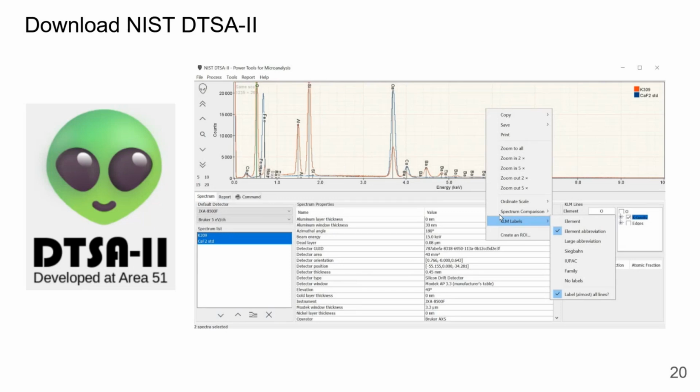So I've commented on hundreds of papers that have issues with their EDX spectrum. And on most of these, it is abundantly clear that they've just made it up. They've taken an EDX spectrum from somewhere else, and then they've labeled it with what particular elements they expected to see in their sample, so that the reviewers, if there were any, would recognize that they did some sort of elemental abundance calculation. So on these, I usually present the spectrum and say, I see issues with this. One, there's hydrogen there. Hydrogen will never produce any peaks. Two, carbon and oxygen have multiple peaks, but will only ever produce one peak each, etc.